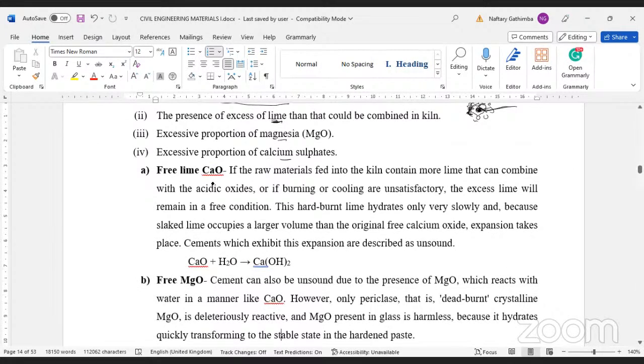If you have too much lime, remember in the raw materials, one of them is limestone. If the raw material fed into the kiln contains more lime than what can combine with the other ingredients from clay or shale, there will be some excess lime in your cement. So this excess lime, calcium oxide, this quick lime, will react when it comes in contact with water to become slaked lime. And you see, this slaked lime expands to a higher volume than calcium oxide, which may lead to expansion. So that's why we're saying, although we have shown the flow process of production of cement, at either of the stages, you need to check.